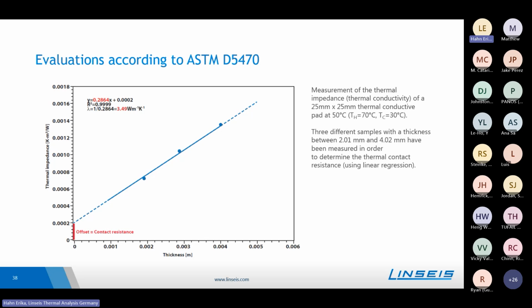And that is done by linear regression, so that we test different sample thicknesses where the variation will be the thermal resistance of the material, but the contact to the meter bars will still be the same, so that we will get in the end a linear relation like that. And out of this curve, we can find out the apparent thermal conductivity of the material, which is the inverse of the slope. And the offset of the curve will correspond then to the contact resistance between the material and the meter bars. So that is how the measurement principle works.